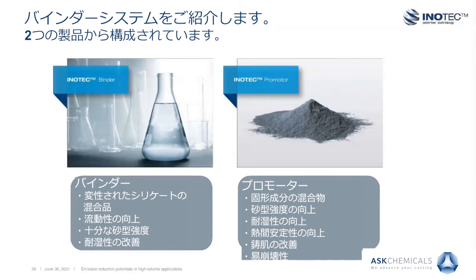Component 2 is the powdered INOTEC promoter, which is a mixture of synthetic and natural raw materials based on a completely inorganic product composition. Through the use of the INOTEC promoter, primarily mechanical and thermophysical parameters during the core production process, but in particular during the casting process, can be adjusted to assure castings of high dimensional accuracy and high surface quality. The main function of this component is to increase immediate core strength for fast ejection in the core production process.